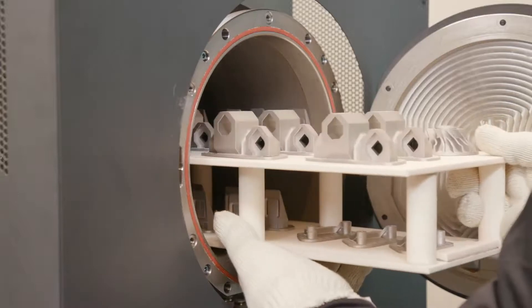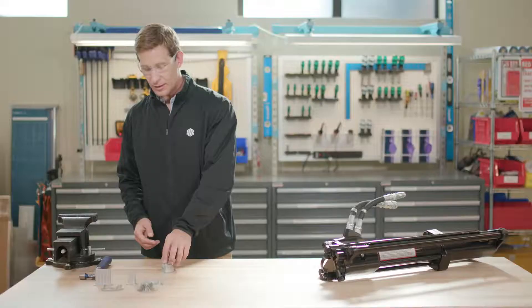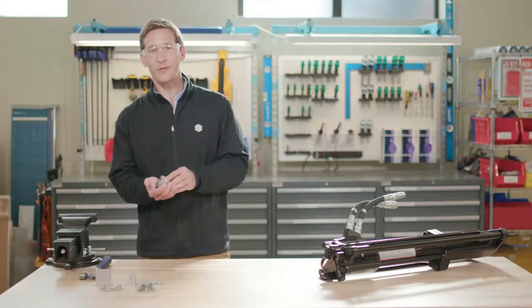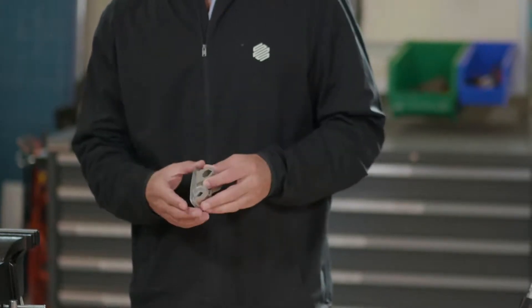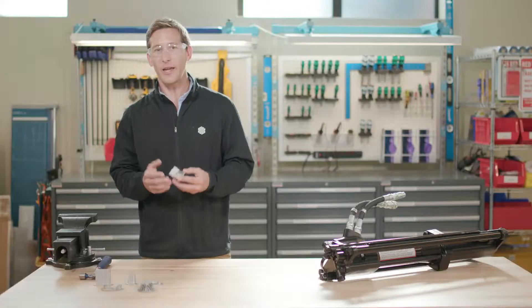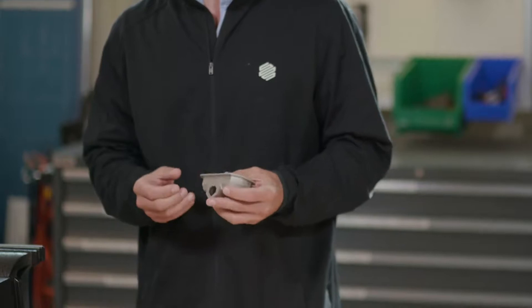Once a run is complete, the setter tray full of finished metal pieces can be removed from the furnace. Once removed from the raft, these parts are ready for use. In the furnace, the layer of printed release material between supports and the raft and your printed part remains powderized. This allows the structure to be tacked to the raft to better control shrink and accuracy throughout the process, but also an easy release after sintering.